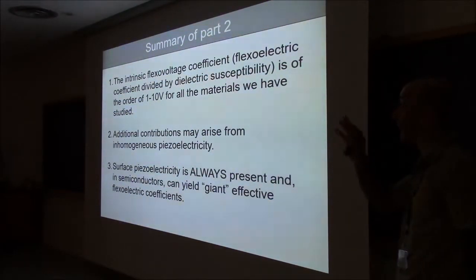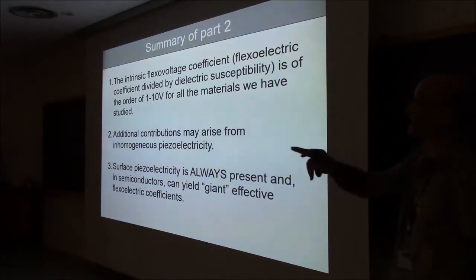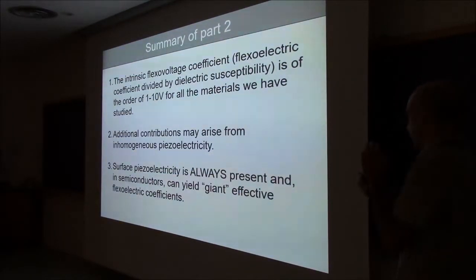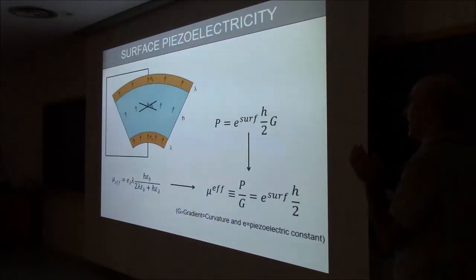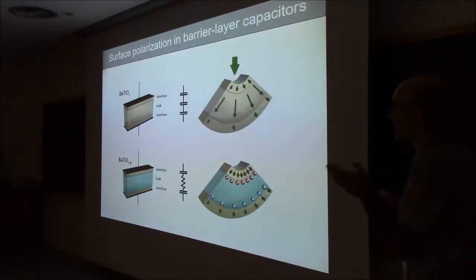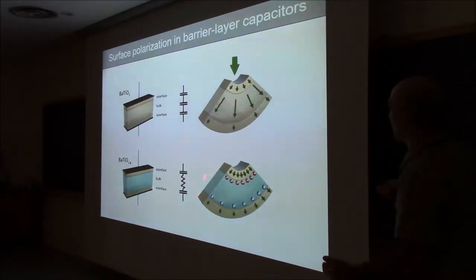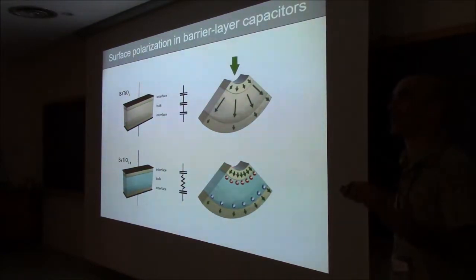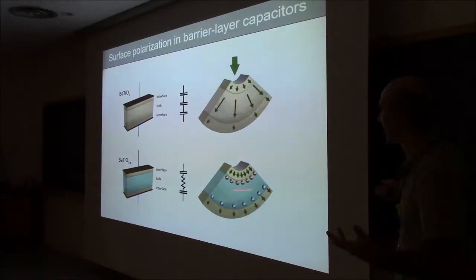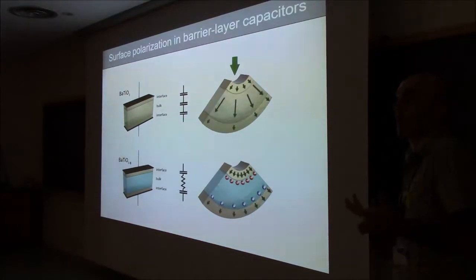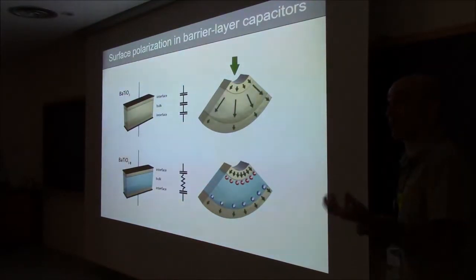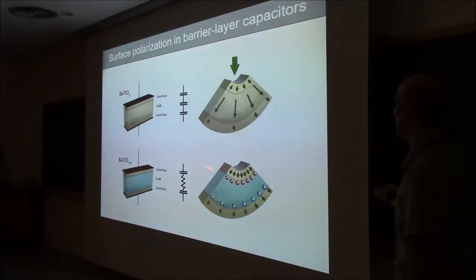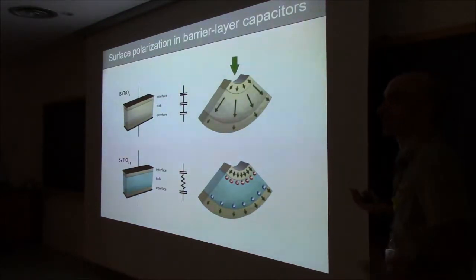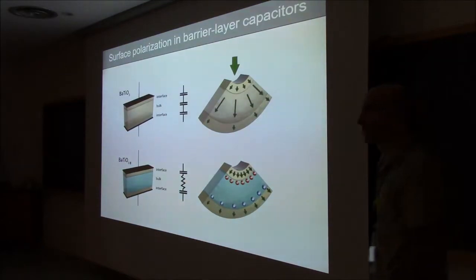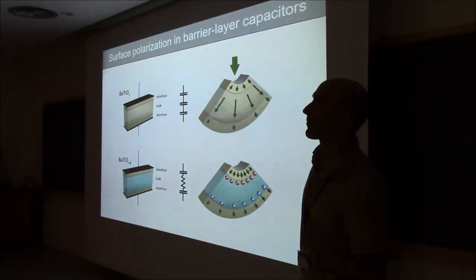You should be careful that you don't push it too far into the metallic phase, because once it's metallic, then you cannot measure it, right? For this semiconductor effect, it is essential that there is the barrier layer, the Schottky contact, something a bit insulating in your sample, in between the electrode and the conductive bulk. There has to be a sufficiently insulating layer, the polarization of which is what you actually measure. If your material is completely metallic, then you don't have this insulating region, and so you don't measure any polarization. In that sense, you can just deposit normal STO on top of the niobium-doped STO. Okay.